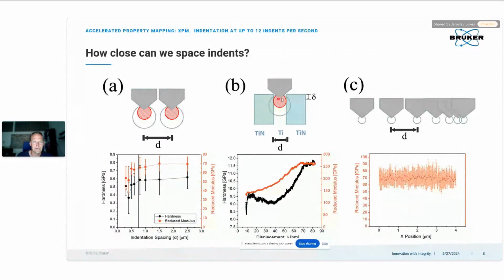If you have different phases which you want to map, you also need to keep your deformation zone local to measure just the intrinsic property of a single phase. If you want to test depths, you can also do a depth profile of mechanical properties. This is the depth profile of hardness and reduced modulus when you are indenting in between two different phases.